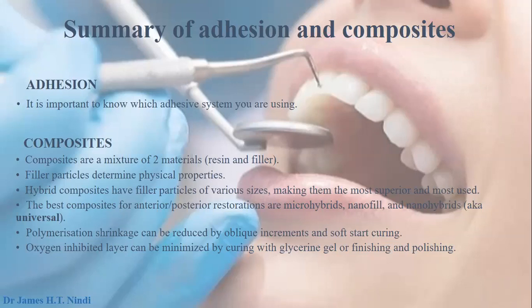We have a major issue with composites. This issue is polymerization shrinkage. This can be reduced in two ways: using oblique increments when placing your composite in the cavity preparations, and also soft start curing by applying this setting in your light cures. And then lastly, the oxygen inhibited layer is something to take into consideration, and this can be minimized by either curing the topmost layer with glycerin gel application or finishing and polishing the composite.